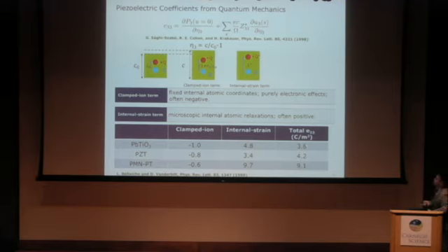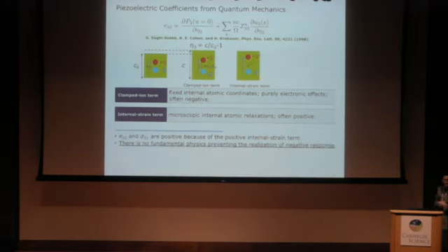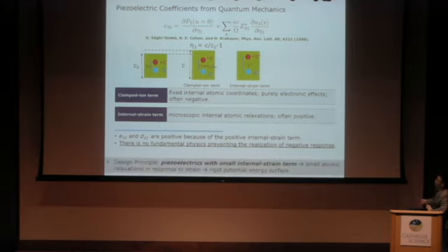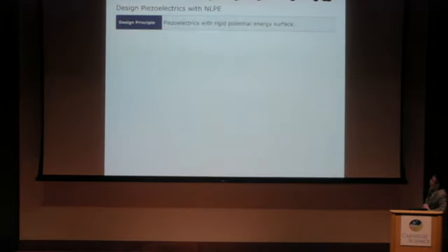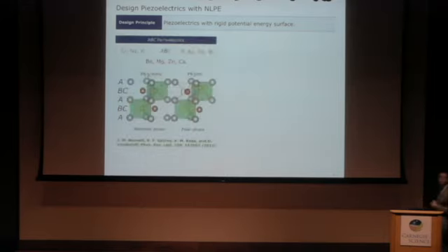But I think from this table we can see that fundamentally there's no physics preventing the realization of a negative response, and this equation actually tells us a very general design principle, that is to find piezoelectric materials with a small internal strain term. As you can see, the internal strain term depends on the Born effective charges and also the atomic relaxations. So piezoelectric materials with a rigid potential energy surface are more likely to support a negative e33 and d33, and this is our general design principle. That is to find materials with rigid chemical bonds. I looked into the literature. One particular class of ferroelectric materials is called hyperferroelectrics. Again, it's from David's group.